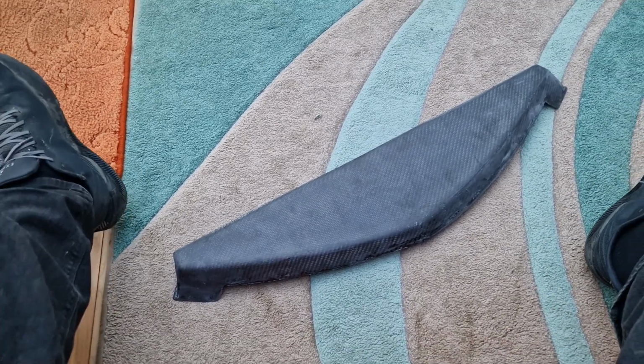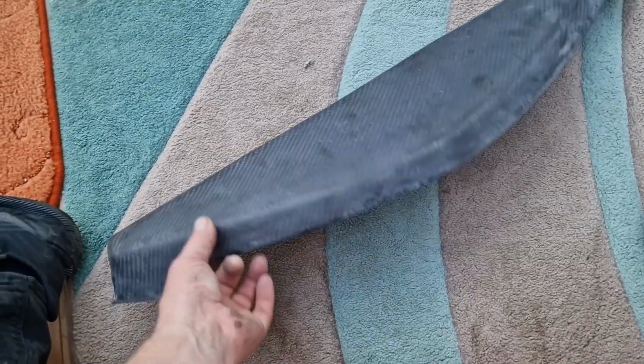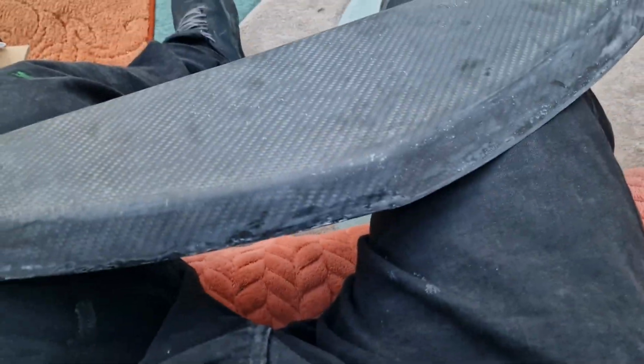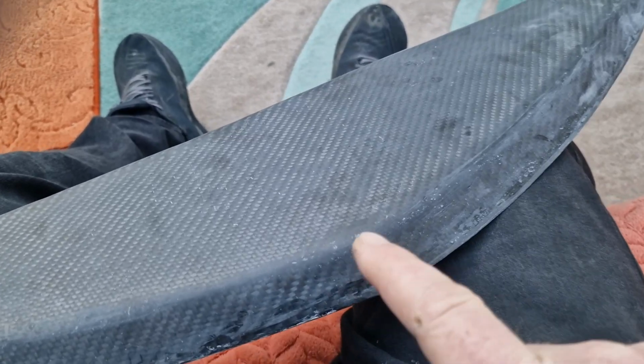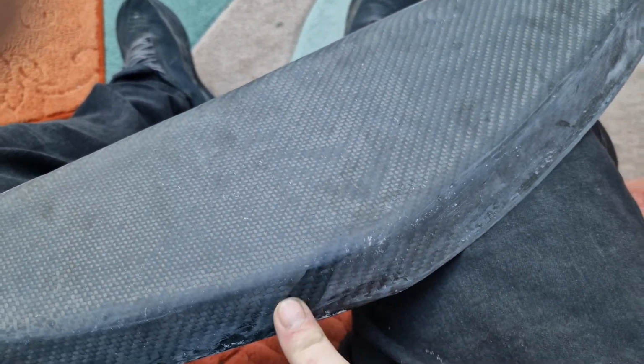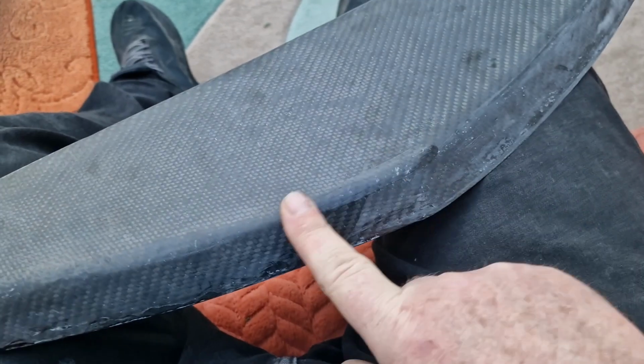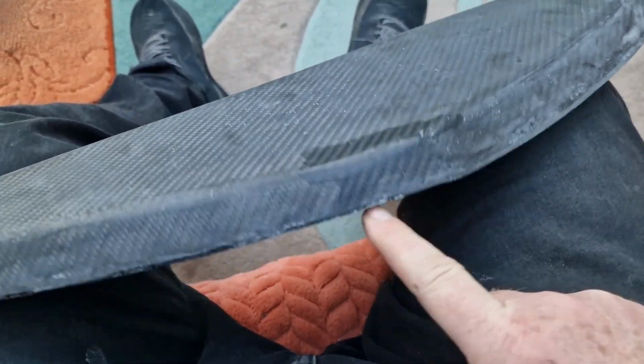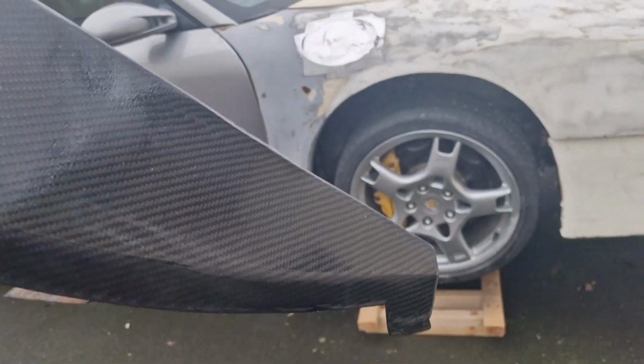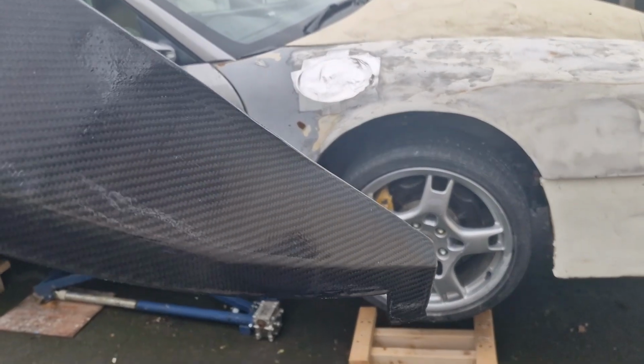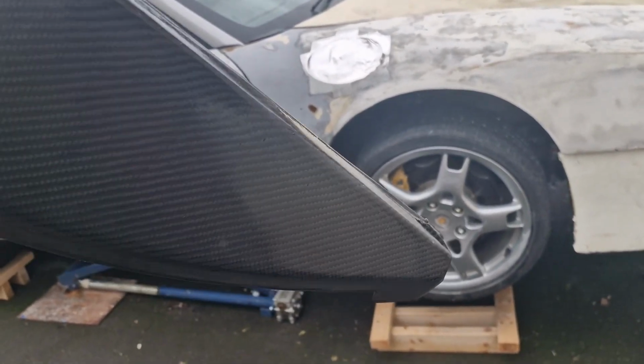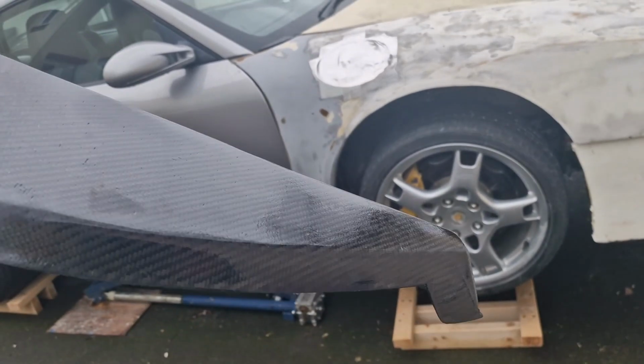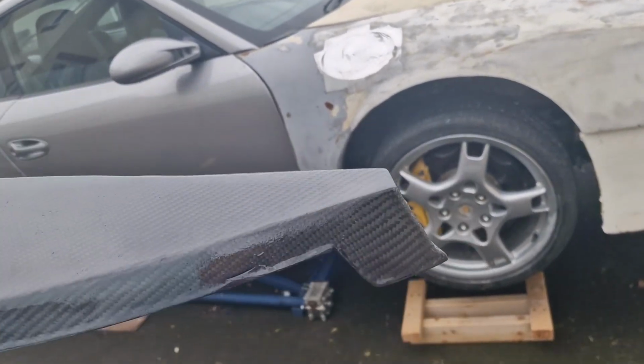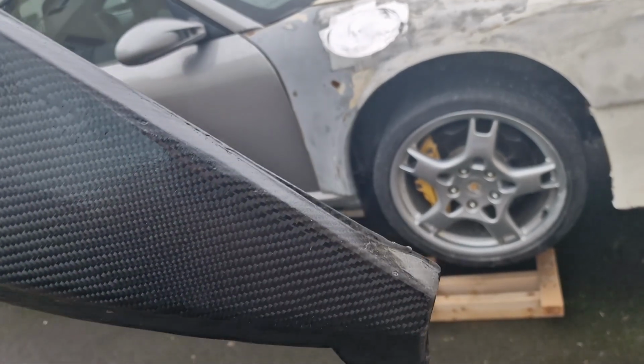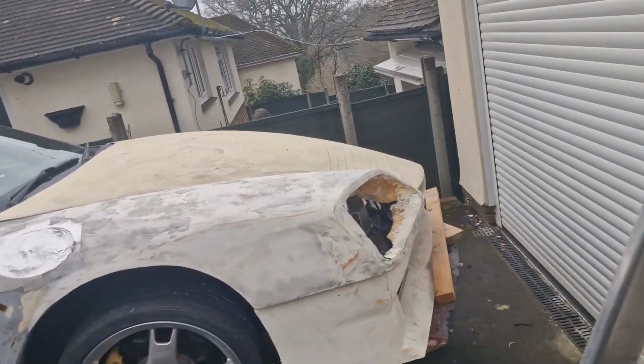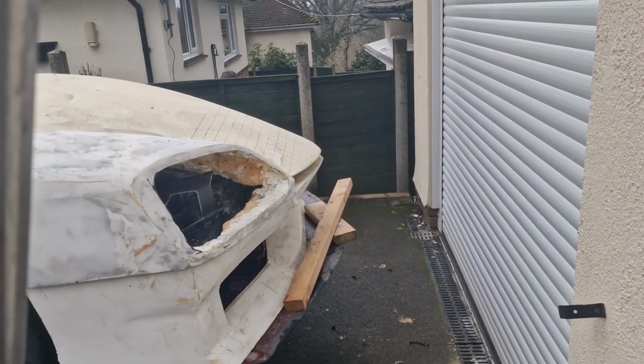If you're wondering what it would look like if you sanded the front too much and exposed the two edges of carbon fibre and the reinforcement in between, well, this is what it looks like. And I'm going to have to add some more resin in there to bond those two together again. Well, I haven't fixed the whole thing because I want to wait to get some more resin mixed up, but I've just had a quick blast of varnish over the top of it, so it looks pretty good to me, and it's going to go on that gap there.